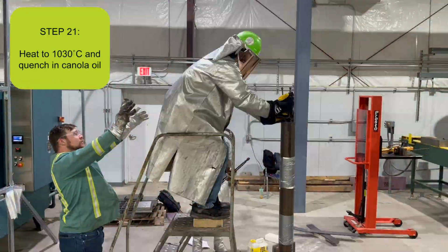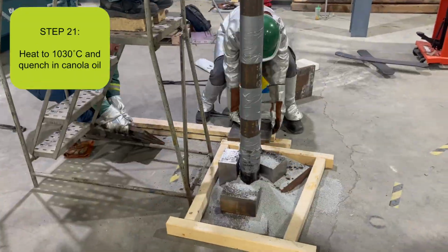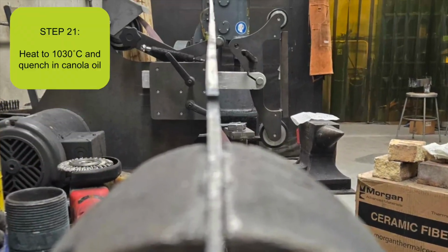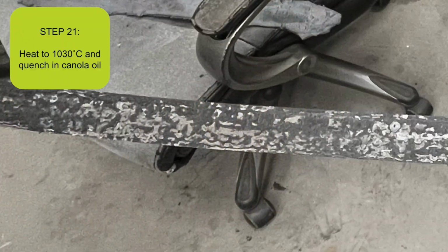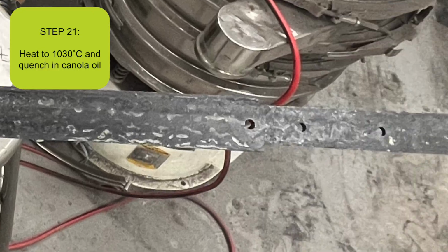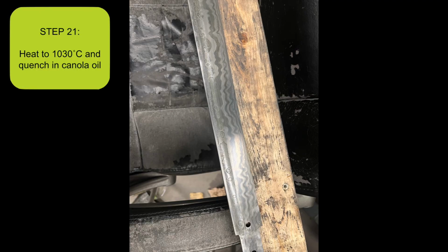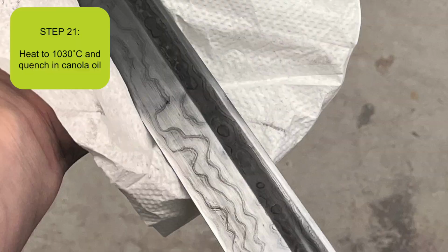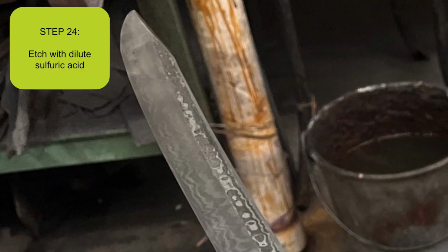It was then reheated to 1030 degrees Celsius for 12 minutes before the final quench, which was done using canola oil. The blade was then tempered and straightened the final time before it was sanded and etched with dilute sulfuric acid. Final assembly was completed using a 2-part epoxy to hold the pieces in place.